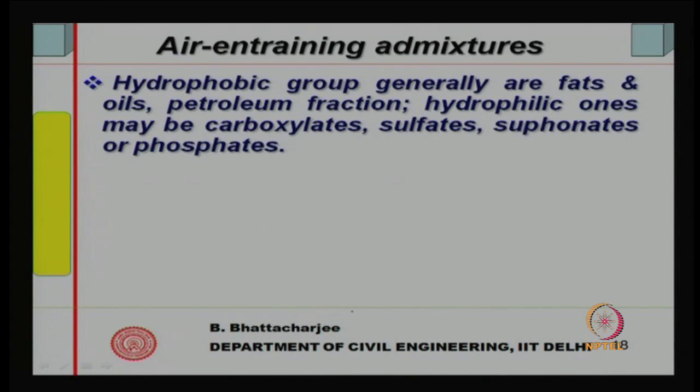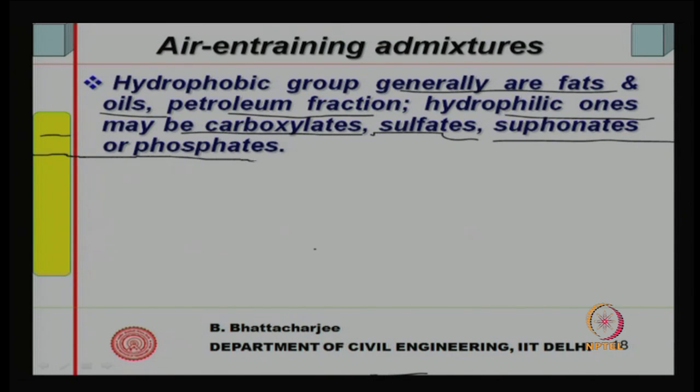Generally, hydrophobic groups are fats, oils, petroleum fractions. Hydrophilic ones are carboxylates, sulfates, sulfonates and phosphates, right. So, these are the ones: largely salts of wood resins, synthetic detergents, salts of petroleum acids, and fatty and resinous acids and their salts.